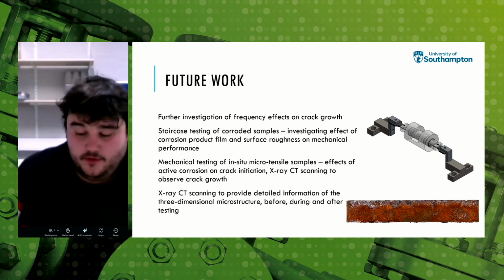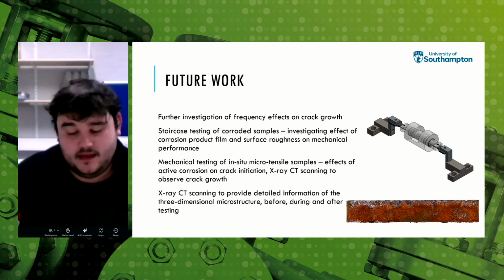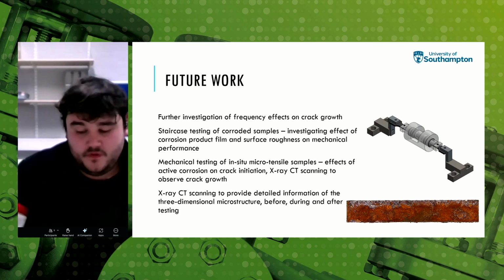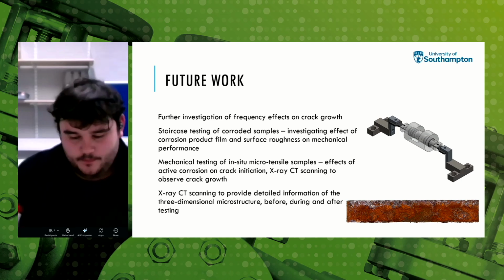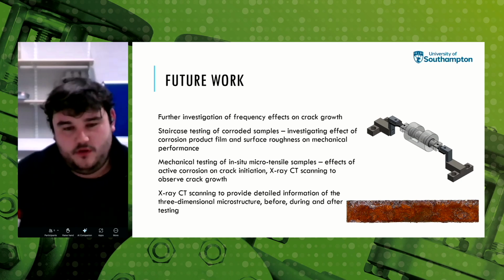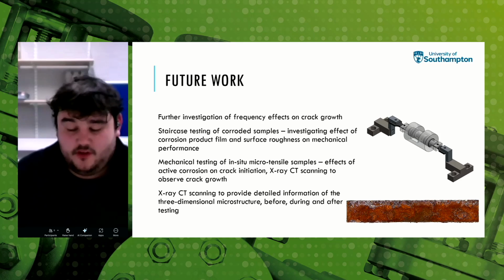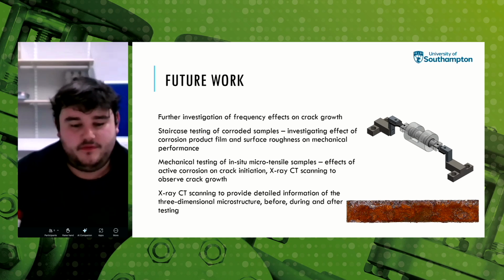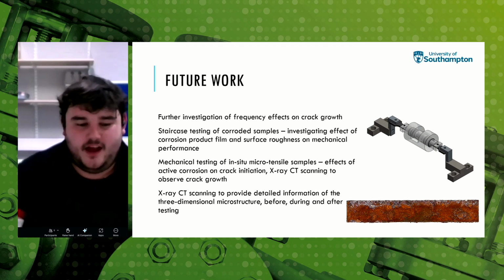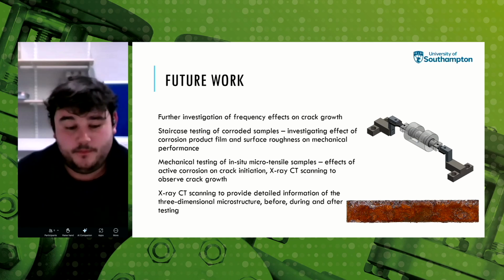We've observed that the frequency of loading appears to affect how rapidly this crack propagates in the material. So further testing needs to be done to look into this. We have a number of samples, ones that you can see on screen, that we've exposed to a salt fog for increasing periods of time to allow a surface roughness to occur and for a coherent corrosion product film to form on that surface. So we can interrogate what is the mechanical impact of these films.